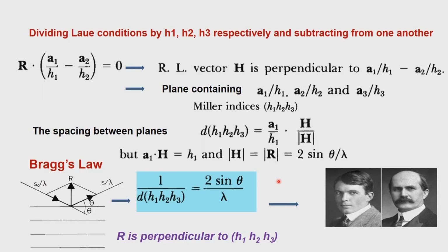The other two equations which we discussed earlier on, the scattering factor and the electron density, represent essentially the presence of the electron density inside this crystal. So, a combination of this to give us the geometry and a combination of the Fourier transform equation to give the electron density, in principle therefore should help in solving the structure. Finding out where the atoms are, what the atoms are, is left to the other two equations. Finding out the environment in which that electron density is placed, because of obeying Laue's conditions and following Bragg's law, we will get the geometry that is associated with the crystal.